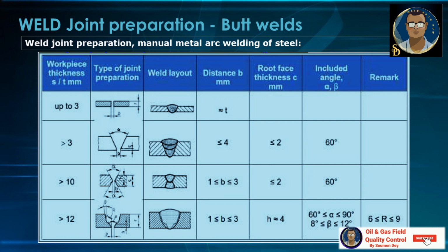If the thickness is greater than 12 mm, then the joint design can be J-type for saving some material and also the time. The root face will be more or less equal to 4 mm and the root gap can be 1 mm to 3 mm. The included angle will vary from 60 degree to 90 degree because the joint will not be single V, it will be J type.